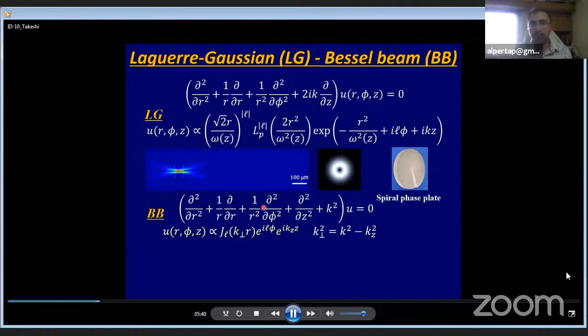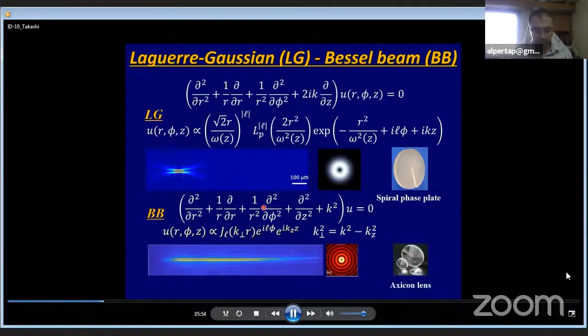It exhibits a non-diffraction effect, namely the wave propagates inside space, but the azimuthal phase and radial amplitude don't change. Okay? It typically exhibits a multiple ring profile with a central dark hole. So a Laguerre-Gaussian mode can be converted by an axicon lens into the Bessel beam. Okay? Such a Laguerre-Gaussian mode or Bessel mode carries the orbital angular momentum determined by this azimuthal phase component. We want to say optical vortex.